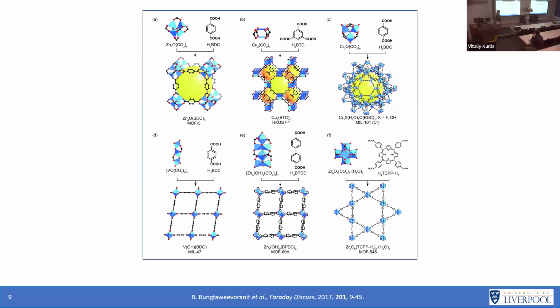So there's a whole different bunch of metal organic frameworks out there. This is a very non-exhaustive list, but essentially you've got MOF5, one of them. We can see that we have this zinc cluster coordinated by a BDC linker to form the material that we saw previously. You can also have copper clusters. This here is a copper cluster coordinated. This is actually another carboxylic acid up here, just hidden slightly. This is another very famous linker that we use in MOF chemistry called benzene tricarboxylate. But you can also see that the same linkers start to show up again and again. Here we've got our BDC linker again, this time coordinated in a chromium structure to form something called MIL101. And then we have other structures where we've got BDC linkers. We also have extended linkers as well. And then we have big, much more functionalized linkers.